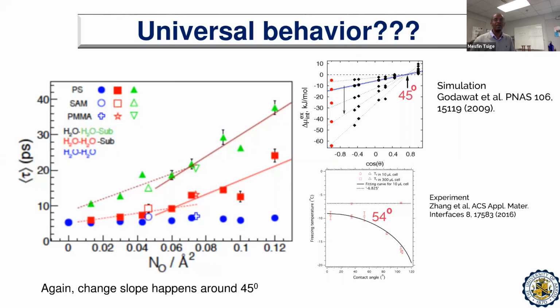And the conclusion we came up with is, if we have interfacial water molecules not involved in any form of hydrogen bonding with the substrate, they should have a universal lifetime of around 6 picoseconds. Whereas the other water molecules, either directly bonded or indirectly bonded, show a dependence that changes the slope around the same contact angle of 45 degrees.